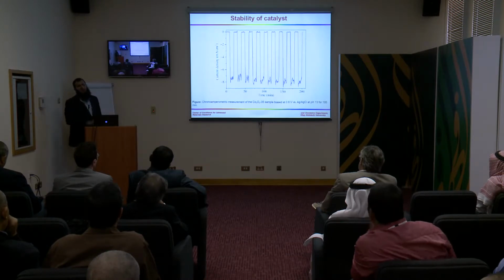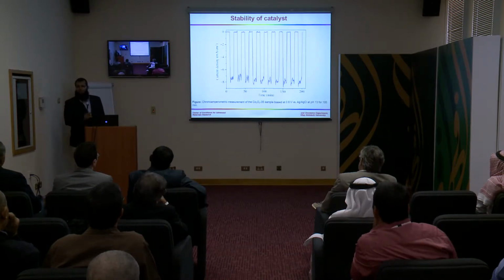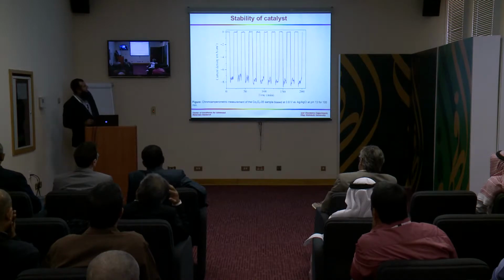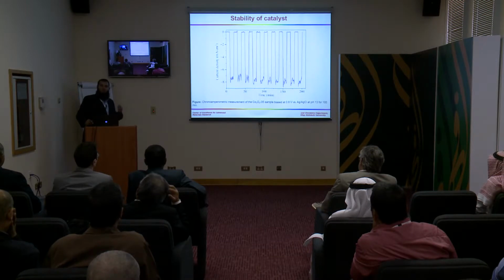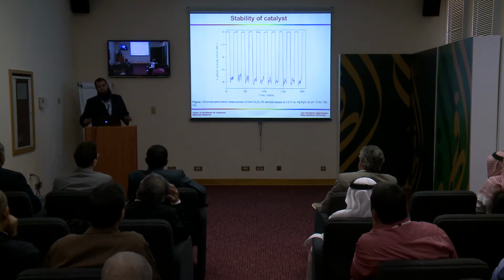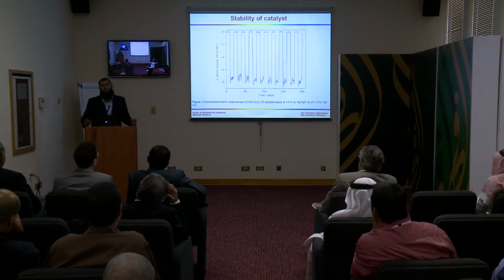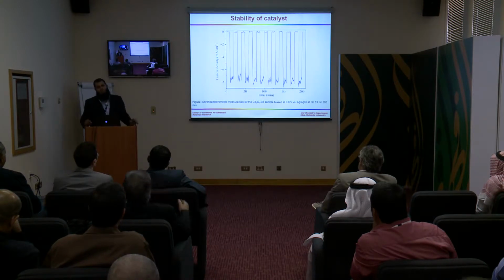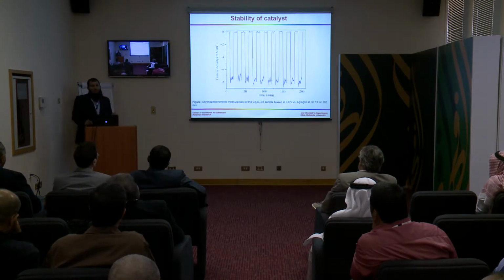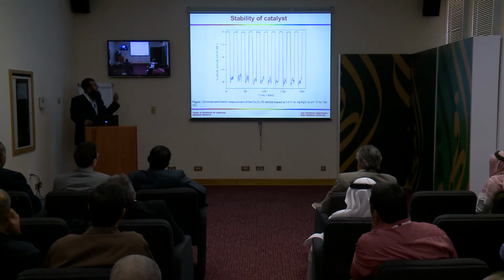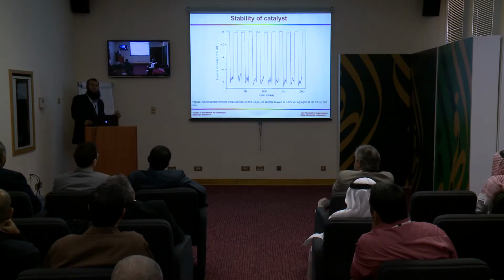The efficiency of the catalyst is important, but at the same time the stability is also an important factor, because different materials have been used as electrocatalysts for water splitting. The well-known materials are ruthenium and iridium oxide, which can be used as the best electrocatalysts. But the problem with these electrocatalysts is their price and their scarcity, and when you apply a high potential and check the stability, they are not stable at high potential.